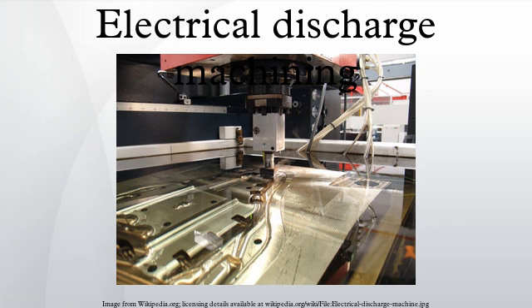Several 100,000 sparks occur per second, with the actual duty cycle carefully controlled by the setup parameters. These controlling cycles are sometimes known as on-time and off-time, which are more formally defined in the literature. The on-time setting determines the length or duration of the spark. Hence, a longer on-time produces a deeper cavity for that spark and all subsequent sparks for that cycle, creating a rougher finish on the workpiece. The reverse is true for a shorter on-time.